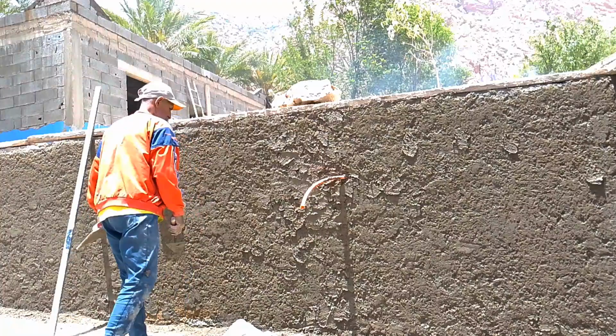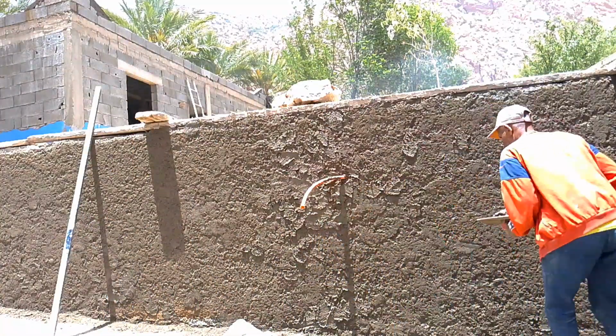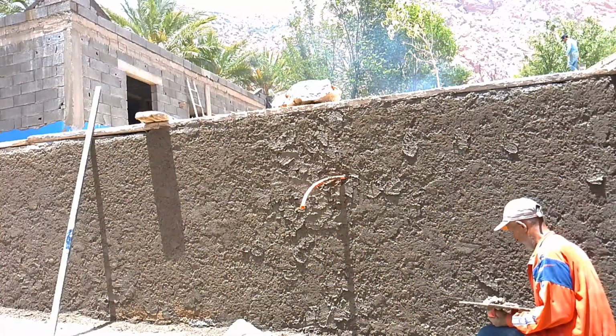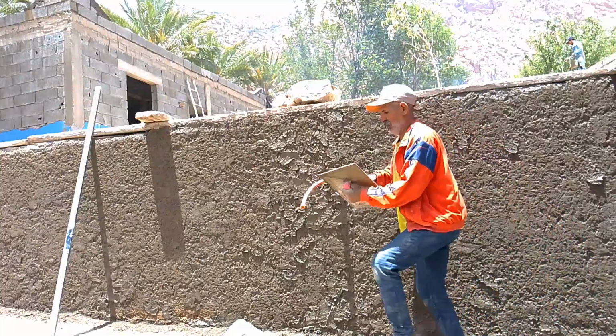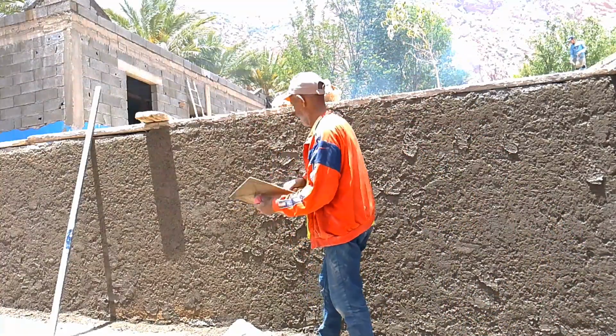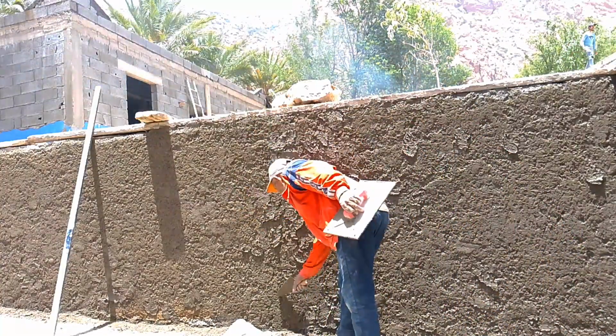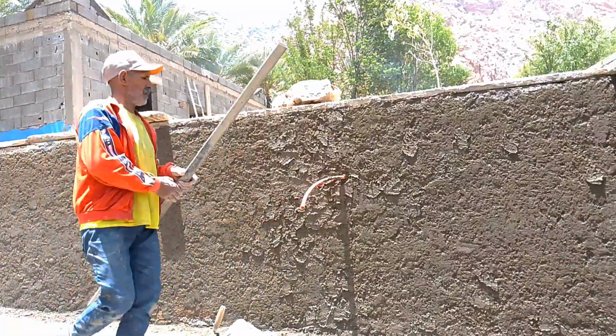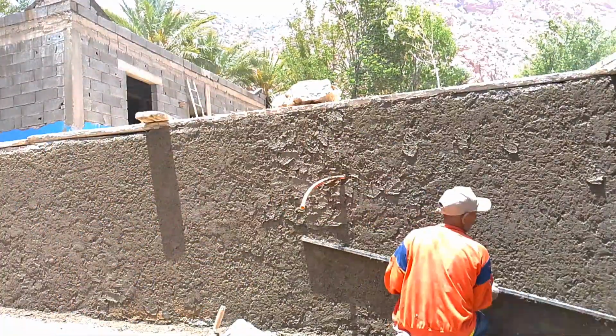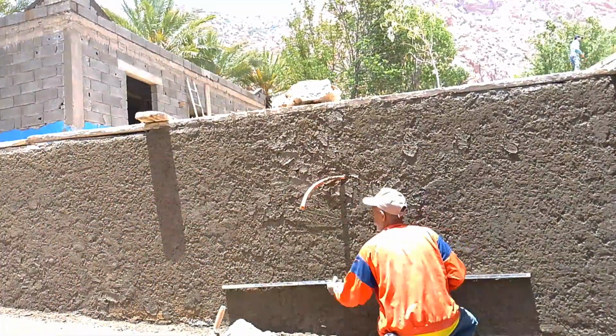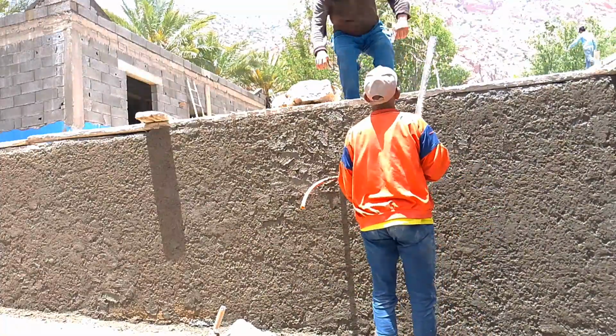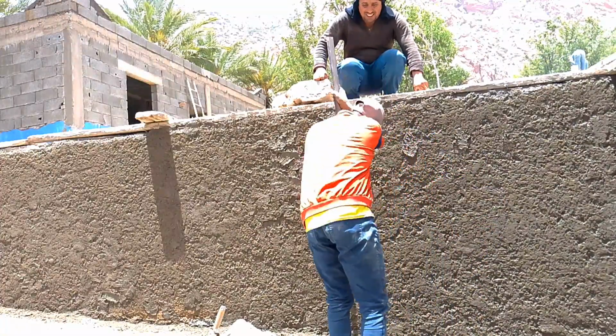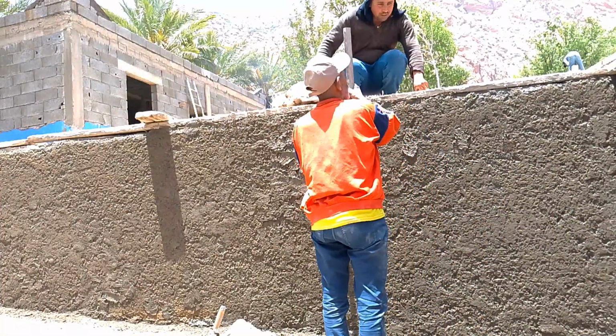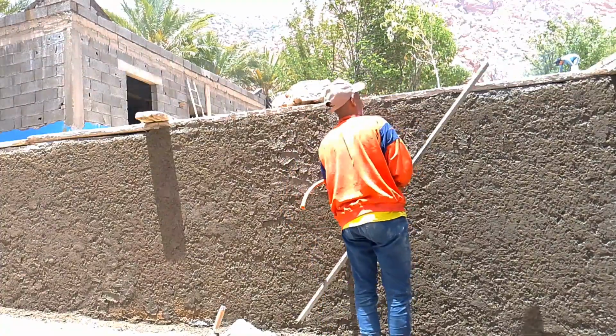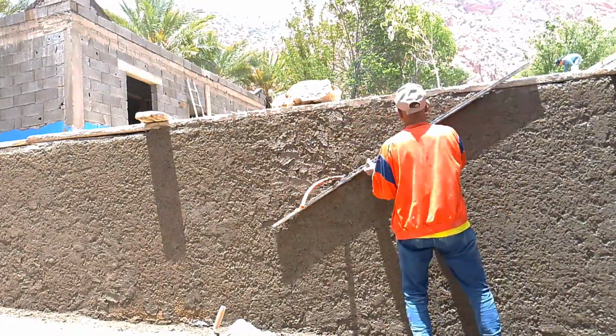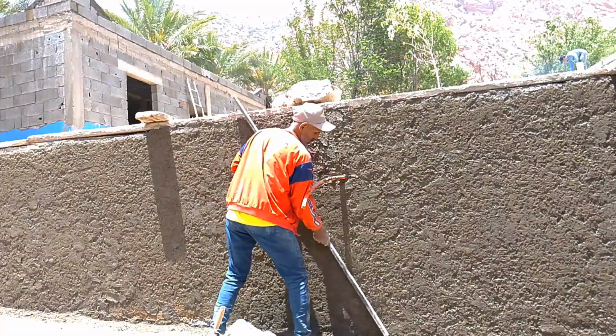3. Dealing with discoloration or efflorescence. Efflorescence is a white powdery residue that may appear on cement surfaces due to moisture pulling salts to the surface. While it's common, it can affect the appearance of your pool wall. Prevention and treatment. Use clean, non-saline water when mixing. Allow proper curing and drainage. Clean lightly with a vinegar solution, 1 part vinegar to 5 parts water. Avoid acid washing unless absolutely necessary.